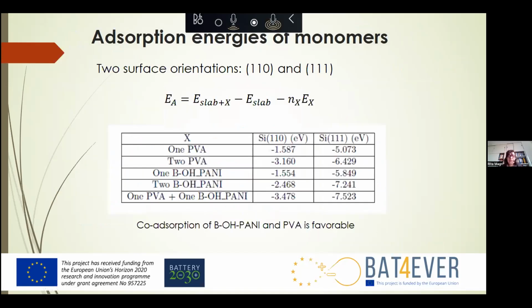And also we have seen, looking at the adsorption energy, that the co-adsorption of both monomers is more favorable than the adsorption of single molecules or two molecules of the same kind.